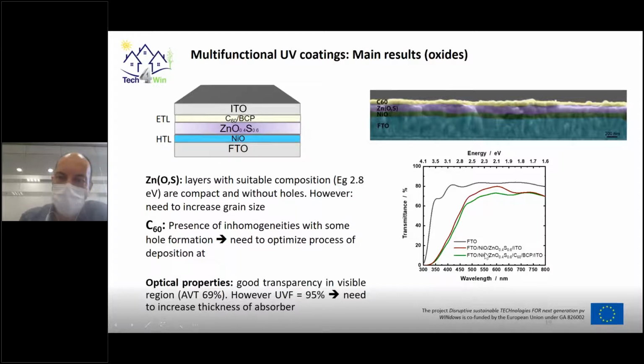In terms of optical properties, we have a very good transparency, almost reaching 70% in the average visible transmittance value, even if the ultraviolet filtering is relatively low. We only achieve about 95% absorption, so we need to increase the ultraviolet absorption in this region. But we think that this will not be critical. I think we will be able to do this just by playing with the thickness of the oxosulfide layer.